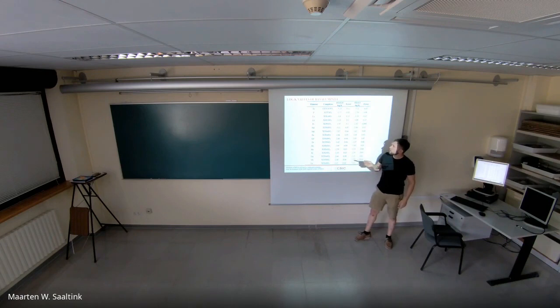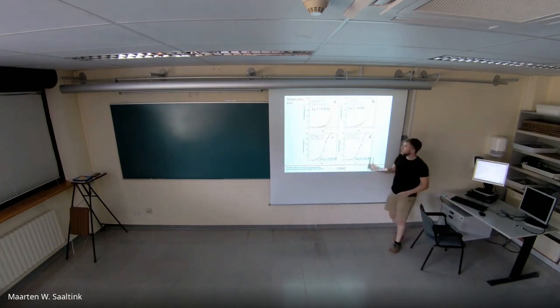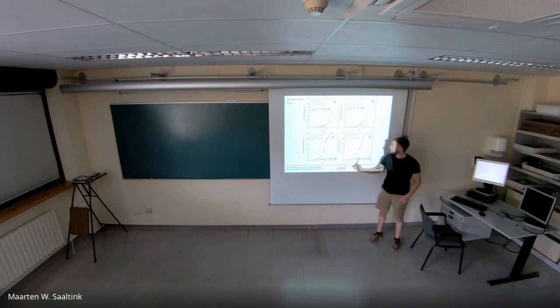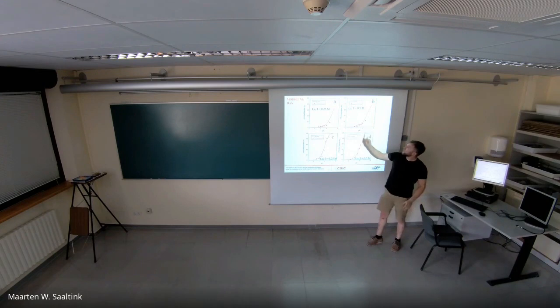So we could say that for this mineral, ionic strength also doesn't have any effect. The models for heavy rare earth elements, which is lutetium, match quite well with monodentate reactions, but with lighter rare earth elements, they don't match so well, but they do follow more or less the same tendency.